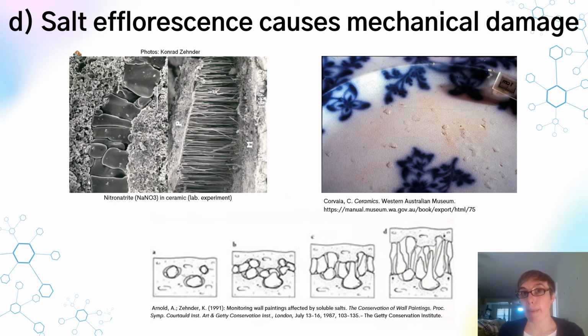We've already talked at length about how the growth of corrosion products within an artifact can lead to significant damage. Well, the same is true of salt crystals. When artifacts from a waterlogged, especially marine environment, are dried and the solvent keeping the salt ions apart evaporates, the salt crystals reform and recrystallize if they're not already involved in corrosion products or other types of mineral products. And they often reform in inconvenient places, such as in the body of a ceramic, or between the ceramic body and the glaze, or inside glass artifacts, and in general in areas that are much smaller than the size of the crystal that ends up growing.